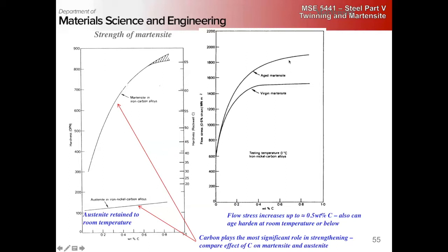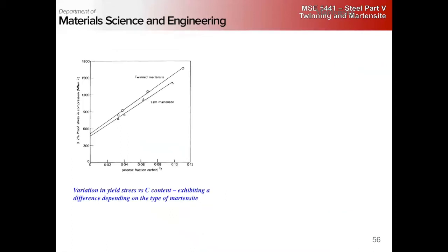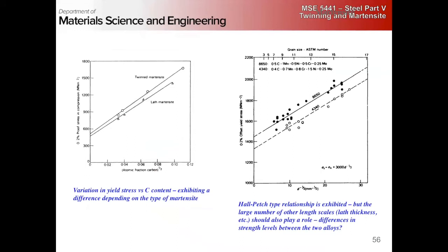And also the strength does increase a little bit with aging, right? As you get some diffusion at room temperature to the grain boundaries, right? So sort of like auto tempering, though that's not really the right word, because you're not diffusing out all the carbon and leaving ferrite, but you do get some motion to the interface. Okay?